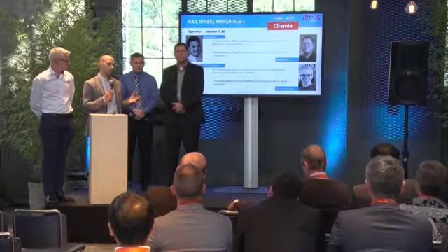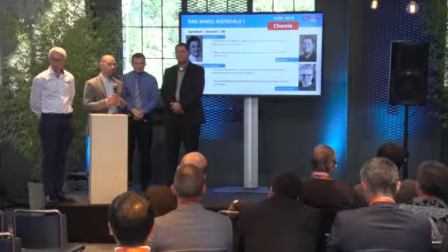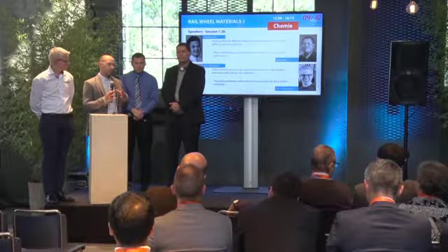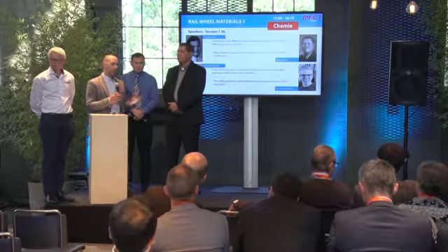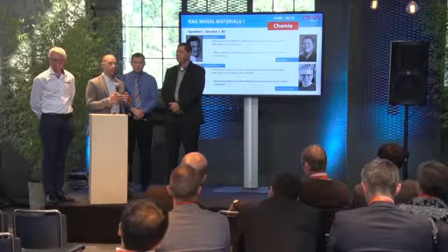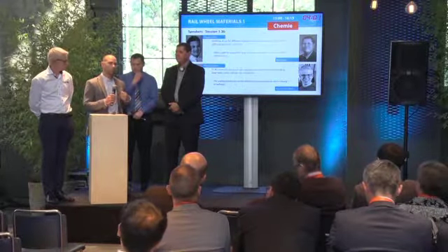One of the benefits of the twin disk machine, the scaled down version, is when we're looking at extreme cases, high slip, that's to our benefit because of the small disk. We can generate extreme heat really quickly, extreme conditions. On the normal rolling conditions, it is a problem. And as I mentioned earlier, it's not quite representative of what's happening in the field. There's things missing like lubricants, friction modifiers, leaves, etc.